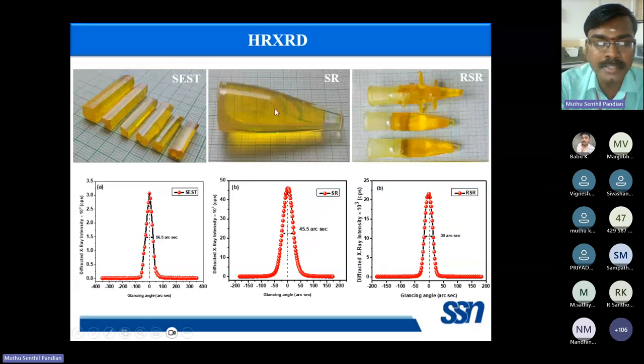We cannot completely avoid impurity segregation even in the RSR method, but we are able to minimize the impurity segregation in the RSR method. So here you see, the FWHM, full width at half maximum, of this RSR method grown crystal is 30 arcsec.